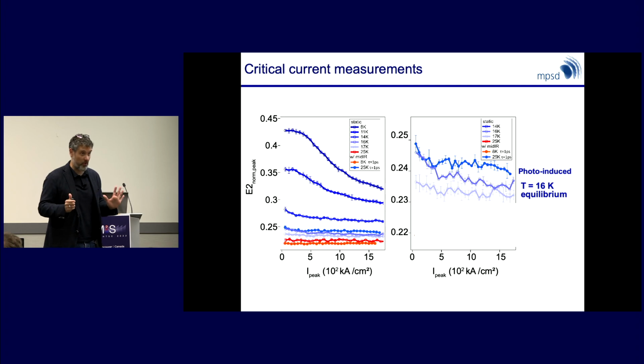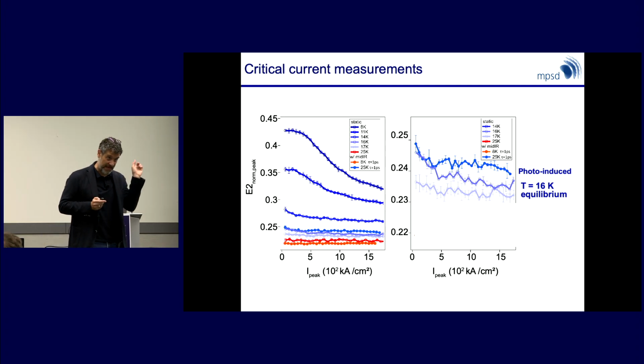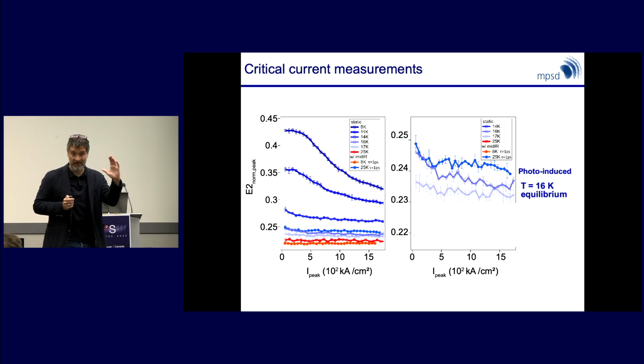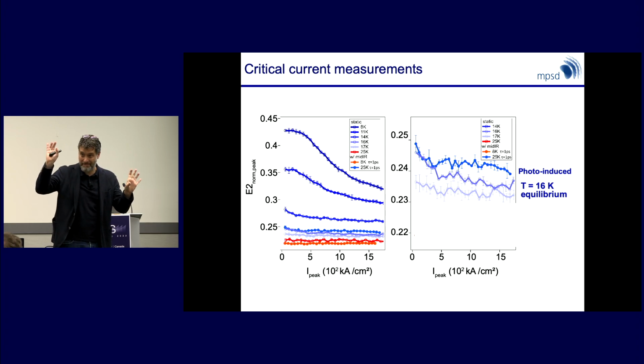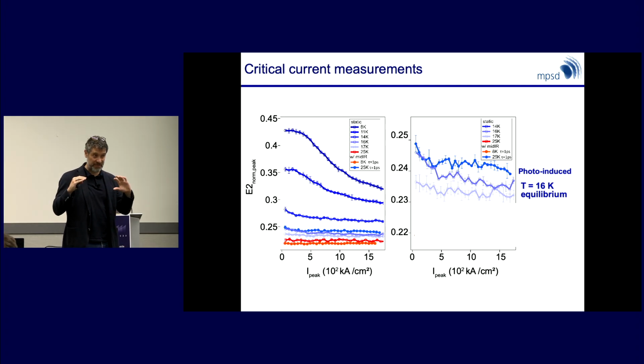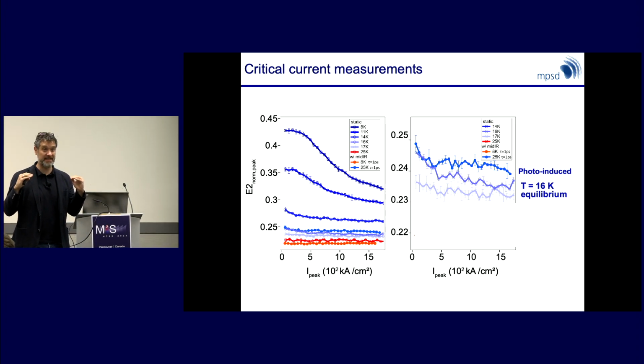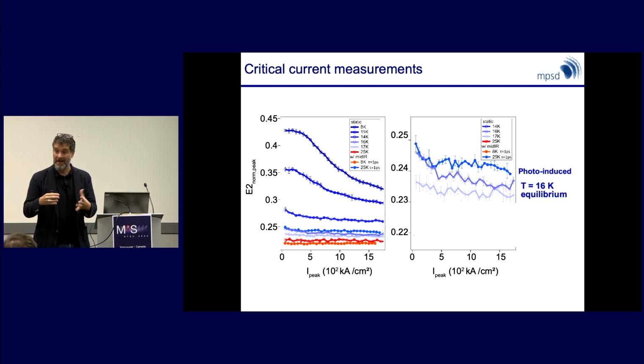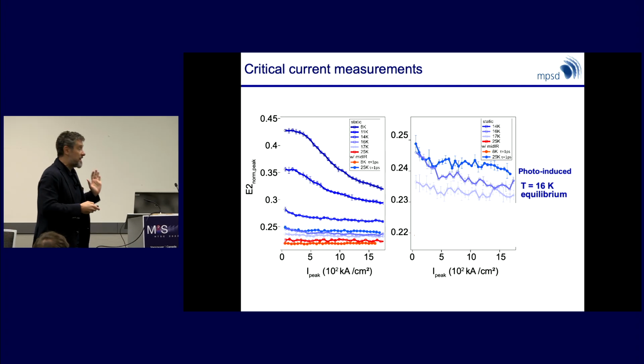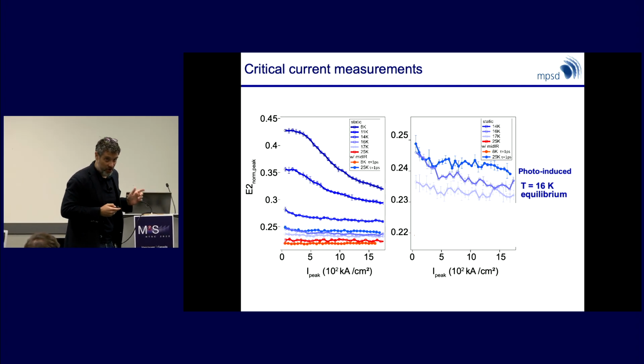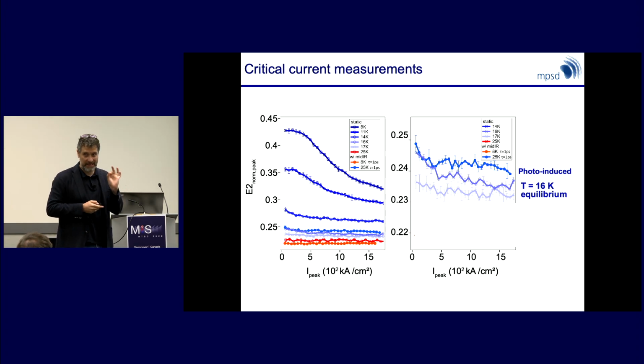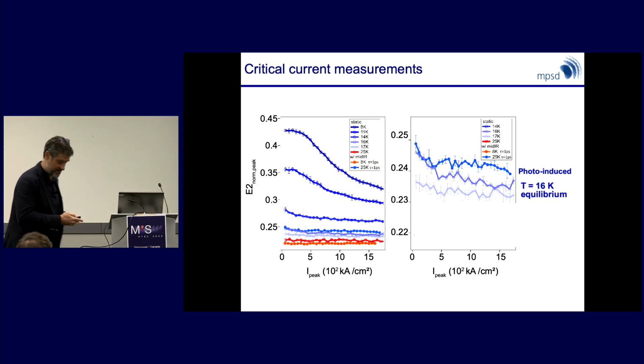It's still a work in progress, but the other thing that I should tell you is that although I don't have the data here, if you do the experiment in the metallic state, and you excite it in the wrong place, where you take a metal and you make it another type of metal, this effect doesn't appear. And if you look at the results below TC, where the physics of this process is that you destroy the superconductor and you make a metal, this effect is also not there. So at least, this nonlinear current response of the photoexcited state is only limited to situations in which we've claimed that the photoinduced state was a photoinduced superconducting state.